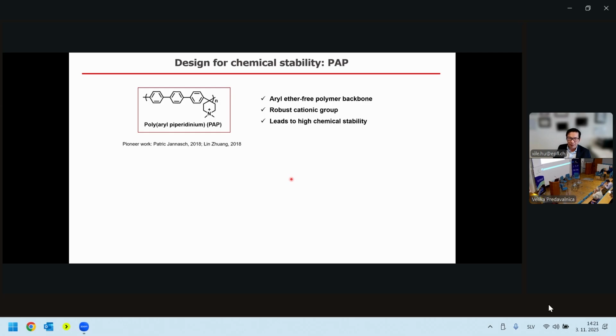And this is actually pioneering work by a professor in Sweden, Patric Jannasch, and also a group in China. What they look at is this aryl ether-free polymer backbone, so pure hydrocarbons. So that's good for hydrolysis. And it has a robust cationic group. I will explain to you why piperidine is robust. Because of this, in principle, they will have high chemical stability. One of the interesting parts is this piperidine, and I will explain why.